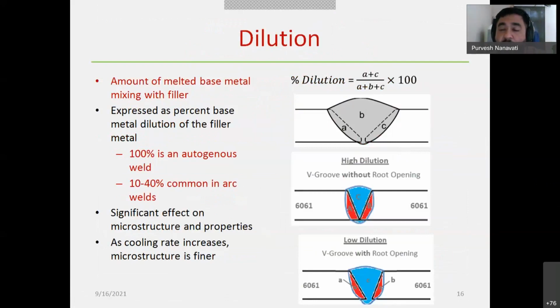Okay, so the next concern is dilution. If you look at the picture, you are joining dissimilar base metals like A and C, which are two metals dissimilar in composition, and you are going to join them with a filler metal, right? Now, this dilution can be calculated using the contribution of the base metal into the weld metal. So A plus C divided by A plus B plus C. A plus B plus C is the total fusion zone chemistry, right? What will be the contribution of base metal into the weld metal as a percentage is known as percentage dilution.